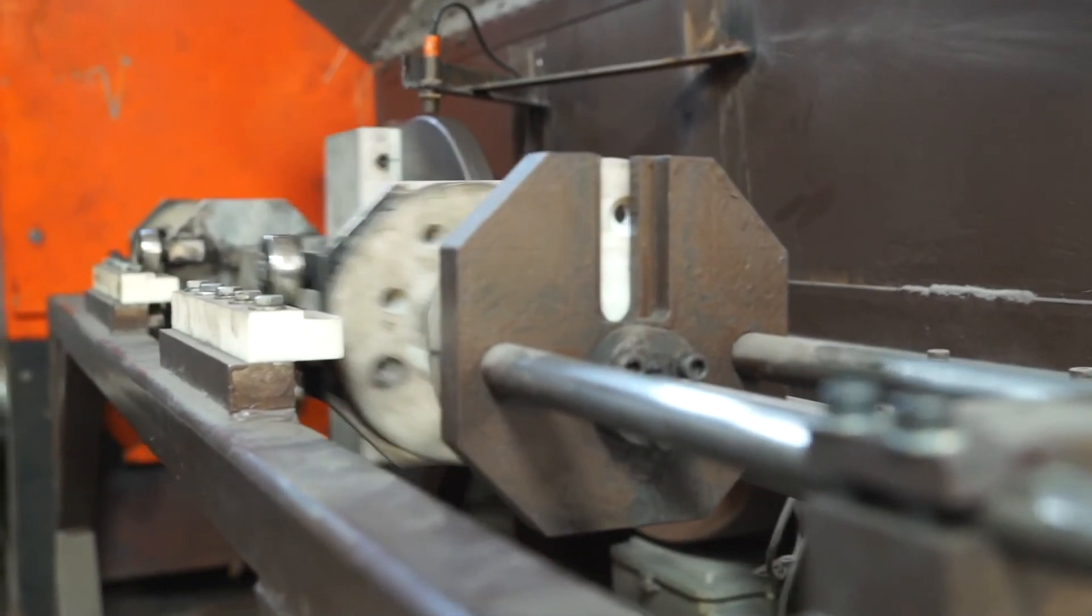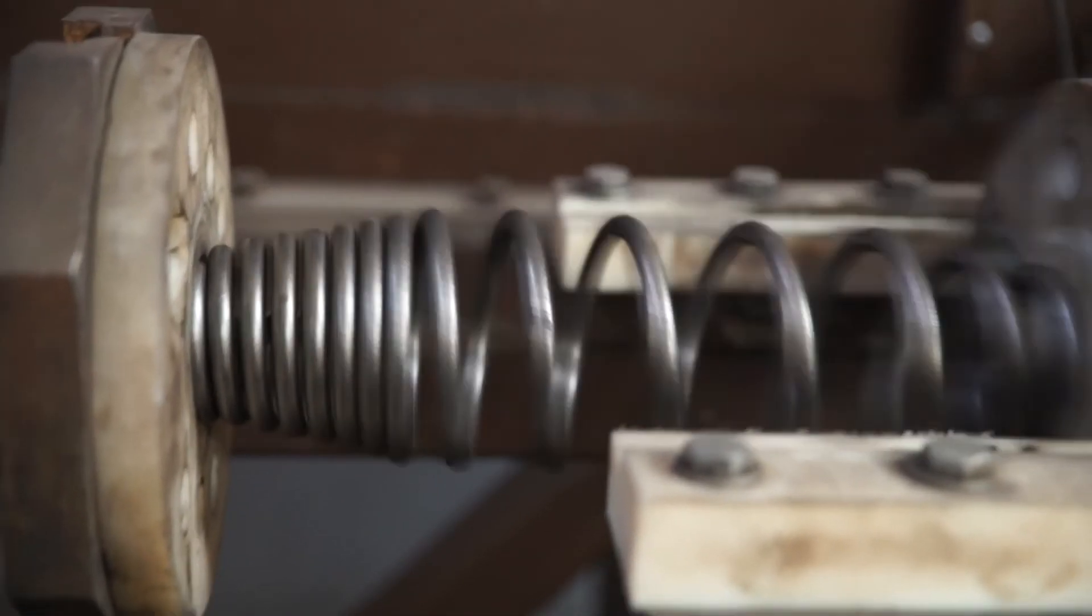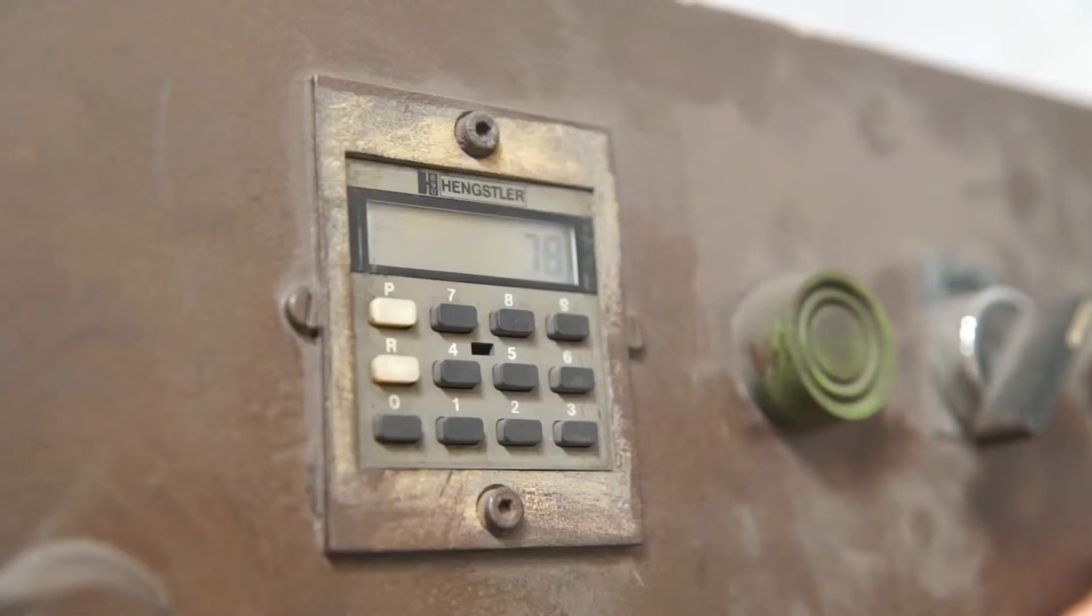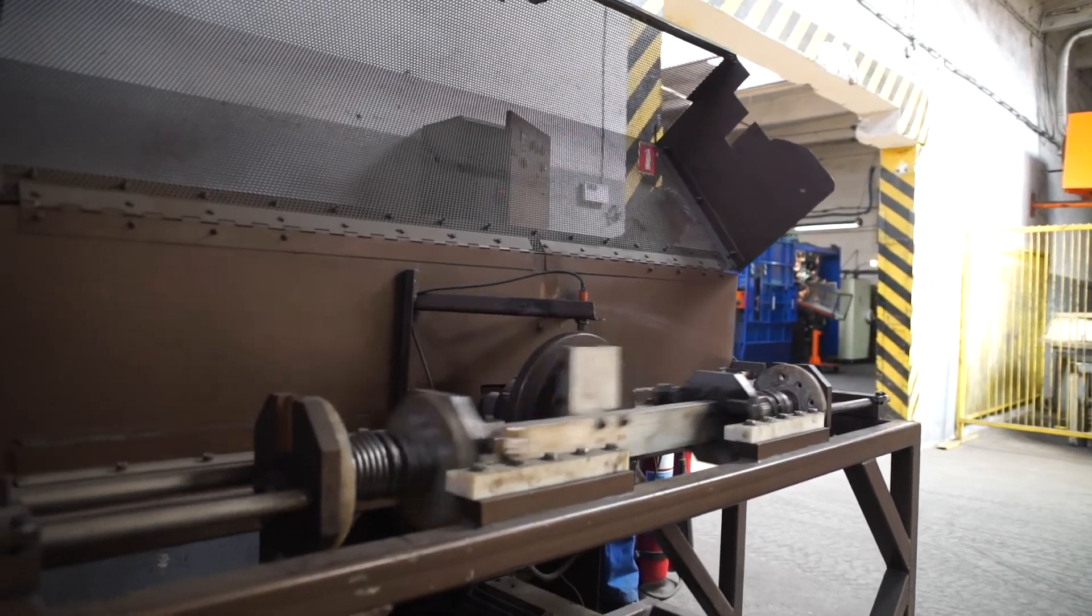Besides laboratory tests, a fatigue test is also carried out, during which the lifetime of the object is checked. If the spring withstands 500,000 cycles during testing, it means that it will work properly.